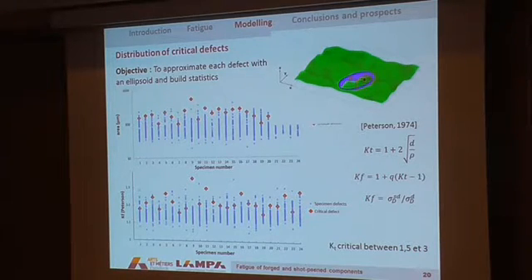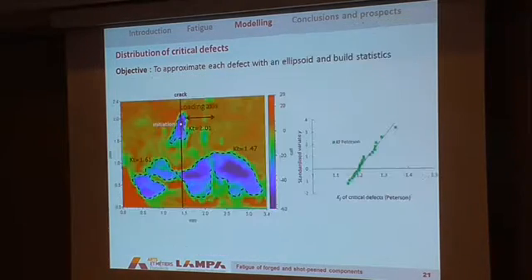We did two things. First, simple things, which consist in approximating each defect with a semi-ellipsoid. You see here this ellipsoid, and we try to build some statistics. If I draw the square root of area for each specimen, for instance for specimen number 1, the blue points represent all the defects. We got something like 100 defects, and the red one is the defect leading to the crack. And the same if I use the Peterson law, the Kf. You see that the result is not that bad. We're able to find a good tendency, but we still don't get every detail of what happens with this simple approximation of the defect.